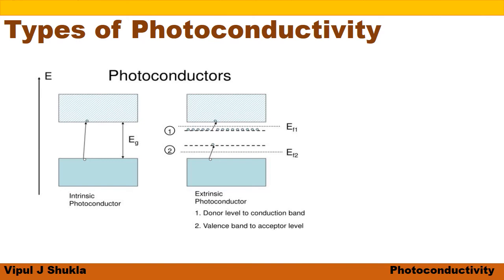The oscillatory slow decay phenomenon is the result of persistent photoconductivity effects attributed to the presence of oxygen-related hole trap states at the surface, which prevent charge carrier recombination. The photocurrent response of zinc oxide could be broadly related to the oxygen vacancies. Such fast photocurrent response times are much more favorable for Schottky type UV detectors. This is one of the important applications of zinc oxide.